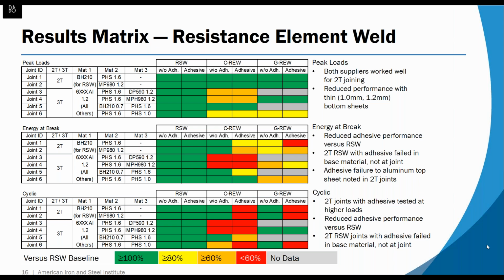For the energy at break, we saw mostly similar results. Anywhere we had difficulty getting to a high peak load, we also saw a corresponding reduction in energy absorption, largely linked to nugget size.